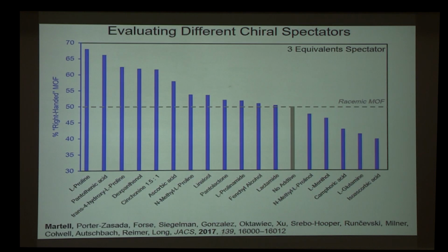So using this workflow, I tested each of these spectators, and the data of the assay are now presented as a single number on the y-axis, where 50% corresponds to the racemic material, which I've shown in gray for orientation.